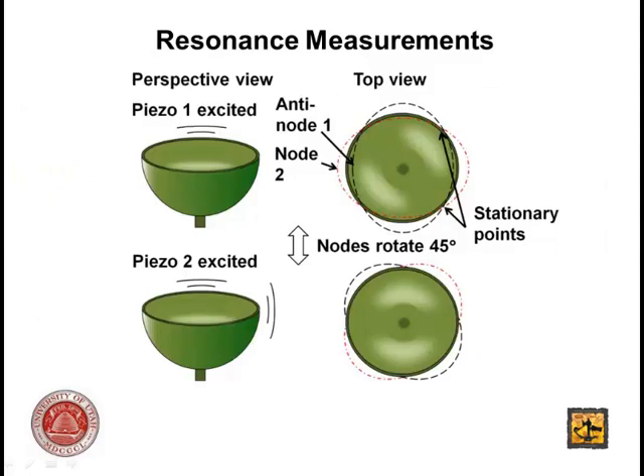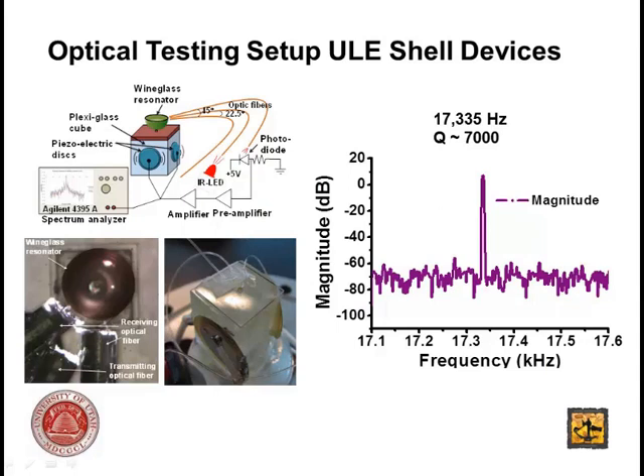So we build several of those structures, and then we perform some measurements. For the gyro application, the important modes of oscillation are these wobbling modes, and it turns out there are a couple of them at 45 degrees. And we can measure the oscillation of these modes using piezoelectric actuators and some optical detection scheme with fiber optics to construct an oscillator.